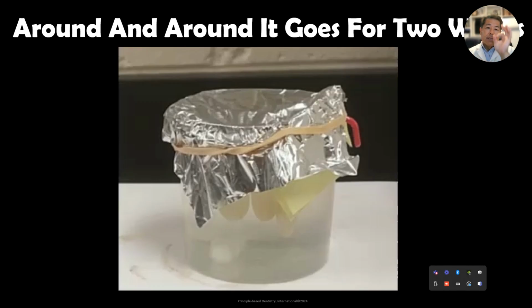There are little composite discs, about quarter-sized, that you can see are suspended in this little plastic beaker. One of these discs is just regular composite. The other disc is the bioactive composite disc that has the Bioglass 45S5 in it. Now, in this beaker of saliva, what would you expect to happen? Well, the composite really shouldn't attract much of the calcium and phosphate. It's basically an inert type of material that's just aesthetic and fills up defects in a tooth. The Bioglass containing composite disc should attract calcium and phosphate to it. So it should have a different looking surface.